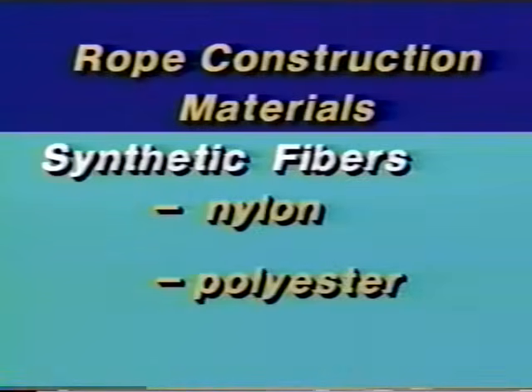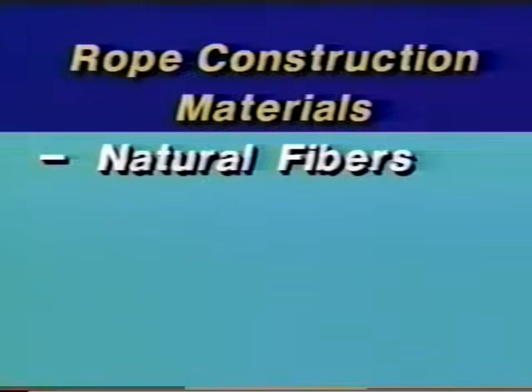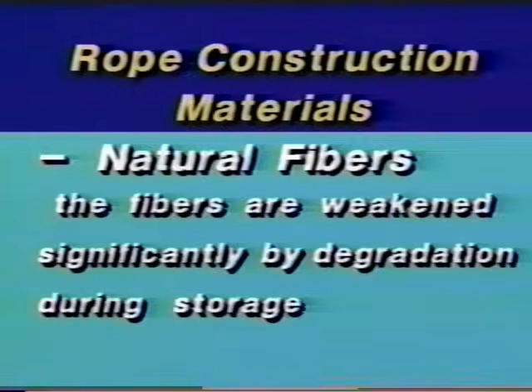The primary reason that we have gone away from natural fiber ropes is because they rot. They just sit there, and the natural humidity in the air causes a degradation of the fibers. And once these fibers begin to degrade, they lose their tensile strength. And once that occurs, it's an irreversible process. We look at polyester or nylon ropes, and after 7 or 8, even 10 years of careful storage, the tensile strength reduction is very minimal, a very small percentage. They also have better flexibility.